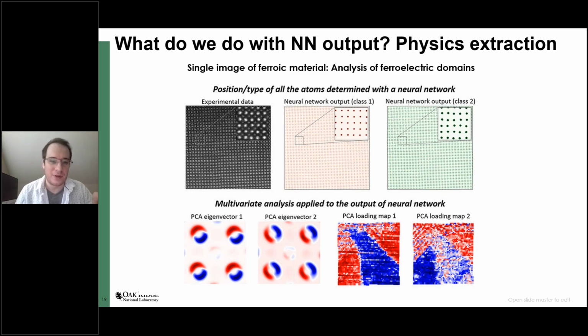So for example, in this example, we had a ferroic material which had two sublattices, so we used a neural network to clean it and to find atoms on each sublattice. And then we cropped images around one of the sublattices and made an image stack. Then we applied classical multivariate analysis to that image stack, which allowed us to find the eigenvectors associated with ferroic distortion in this material. And so we see the type of distortion happening in each unit cell and where these distortions are in a larger image. So that's one example.